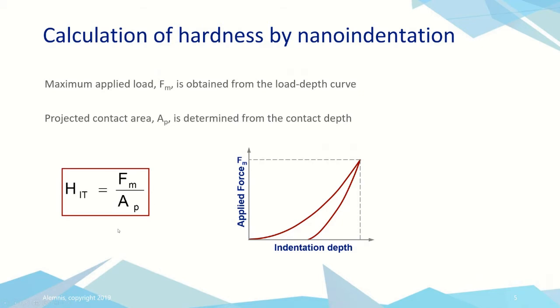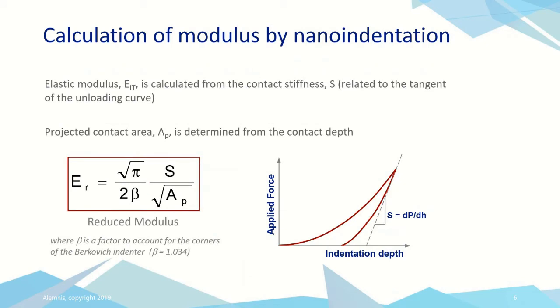So simple equation will give us HIT, which is the hardness. IT shows that it's by instrumented indentation per the ISO 14577 standard. Now, in addition to hardness, we can also calculate the elastic modulus, as you can see here. So for this, we basically take the tangent of the unloading curve, and this gives us S, the contact stiffness, which is directly related to the reduced modulus E. Okay. Beta here is a factor accounting for the shape of the indenter that was used. And if we know the Poisson's ratio of the material, then we can also calculate the true elastic modulus.